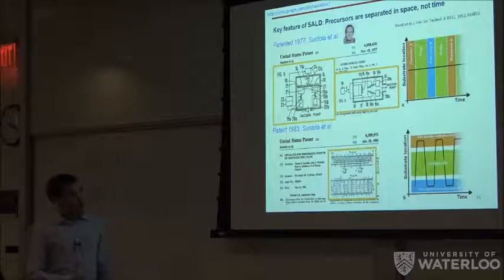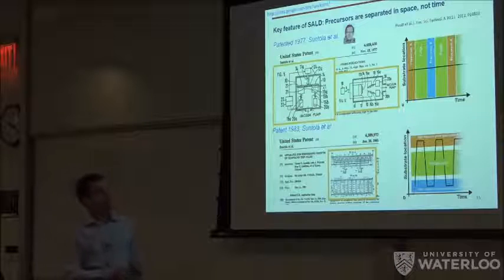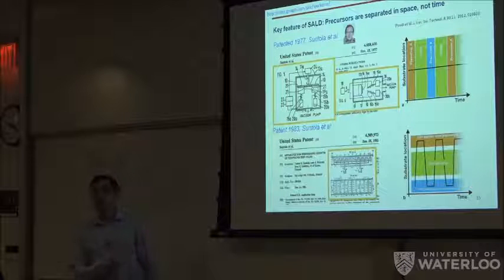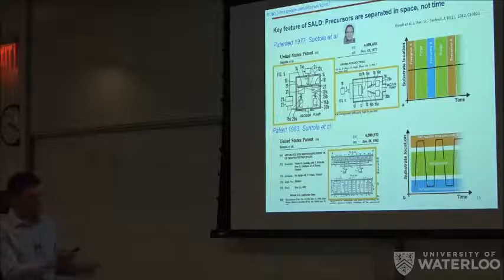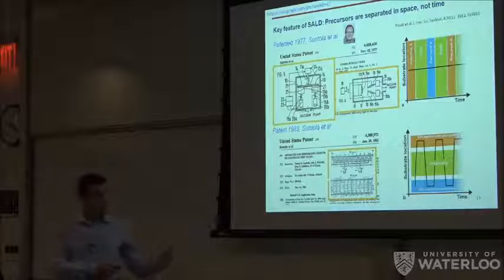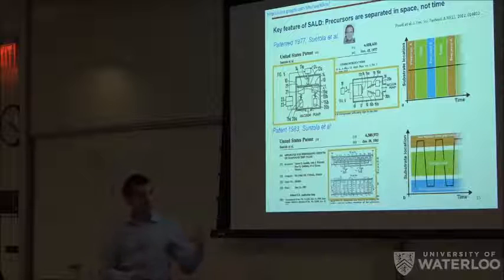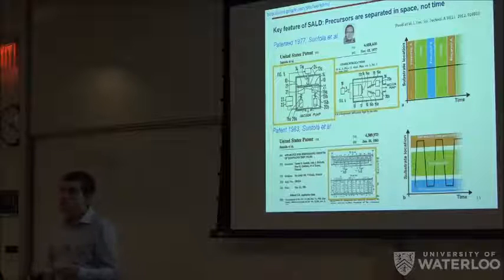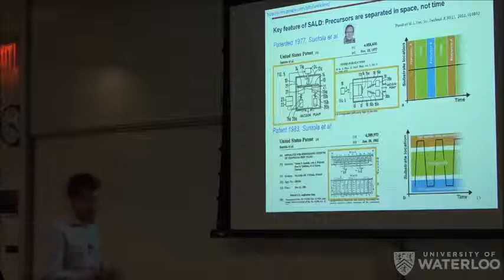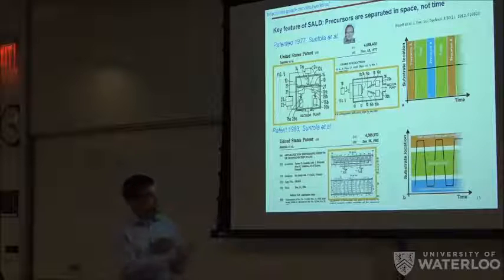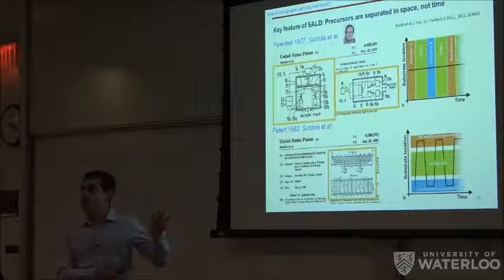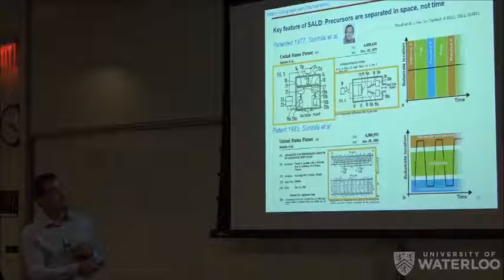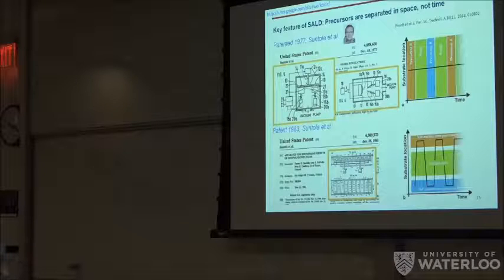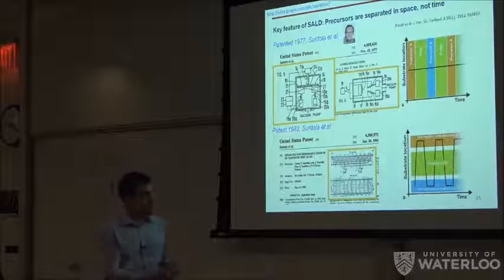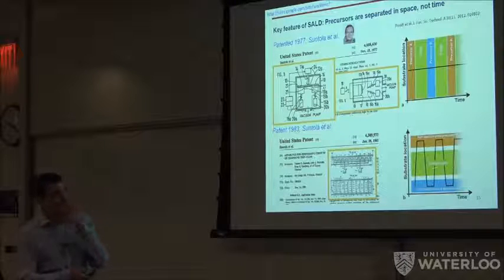He then developed it a bit further, and in 1983, he realized that he could do that without using vacuum, by using a gas flow, which could keep apart the two precursors. And by doing it in this way, you can come up with systems in which you can do this processing even at atmospheric pressure. So it's quite remarkable. And despite that, and despite the date, pretty much all the commercial ALD was done in this temporal configuration under vacuum. So it was only, before, to see more the analogy between the different approaches, you see immediately that in this case it's much faster.